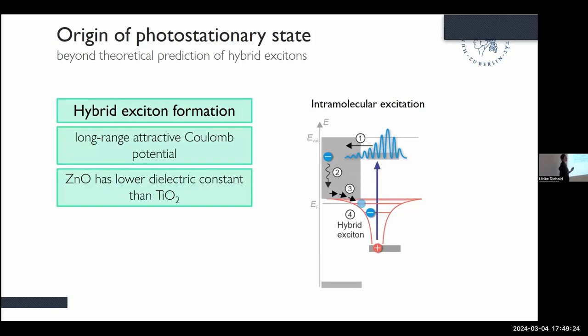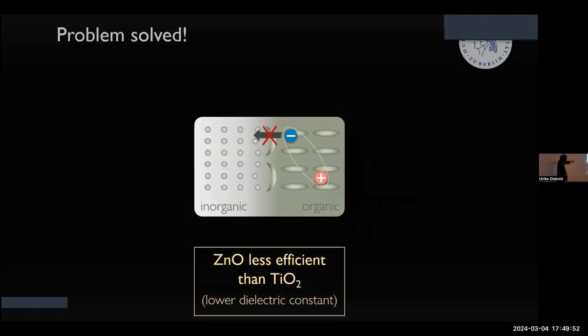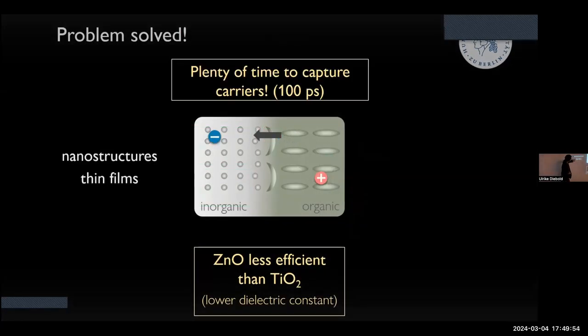And all this interpretation is supported by all these core shell works where they add a screening material to the zinc oxide nanostructures, and suddenly they can charge separate. It's like the Coulomb potential is further screened, it's narrowed down, and then the electrons can stay away. This is, sorry, it's here on this slide. We have a lot of time. We have 100 picoseconds with the electrons in the bulk.